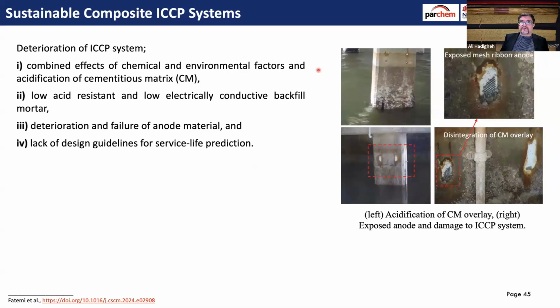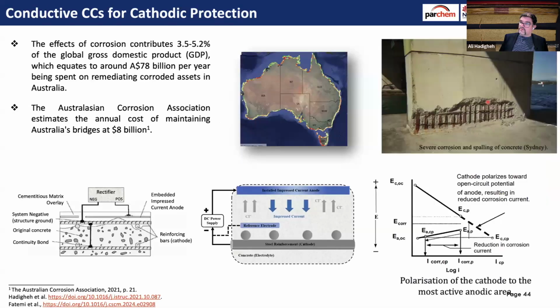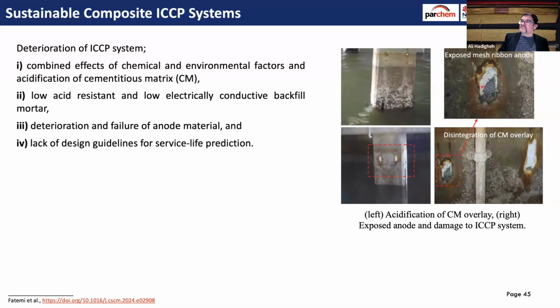So the challenge that our industry partner had was they applied these ICCP or cathodic protection systems onto their bridges, but the system, how it works, is basically that there's reinforcement, and they embed an impressed current anode into the surface, and then they embed it within the concrete. And what it does is it takes the chloride ions away from steel reinforcement and takes them out of the system. So it's basically, instead of chloride ions exchanging with reinforcement, they try to avoid that, and they impress the system within that environment. But the challenge that they had was acidification of the mortar on those anodes.